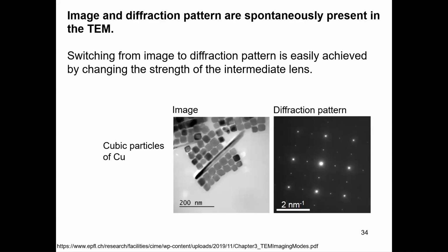The TEM, if your samples have crystalline structures, we can do imaging and also get diffraction pattern at the same time. The switching between imaging mode and diffraction pattern mode is really easy. We have to change the strength of the intermediate lenses and also take out one objective aperture and then put a different aperture, and we can get, so this is the example of copper cubic particles. Image shows here and then diffraction pattern.